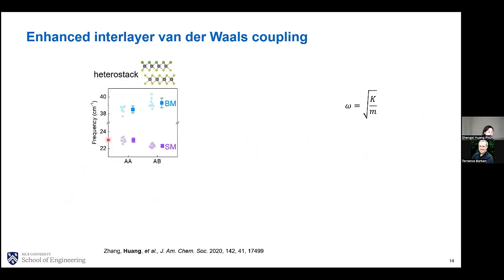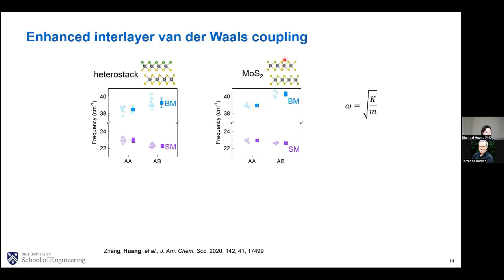And here I summarize the frequencies for these interlayer Raman modes. You can see the breathing mode and shear mode over here. For comparison, we also perform the same measurements for the bilayer 2D materials, as you can see over here. If we just compare their frequencies, we can see there is already a little bit of difference. But now we can use this equation to calculate the K, and we can compare the K between the Janus heterostack and MoS2 homostack. So now here's the result.